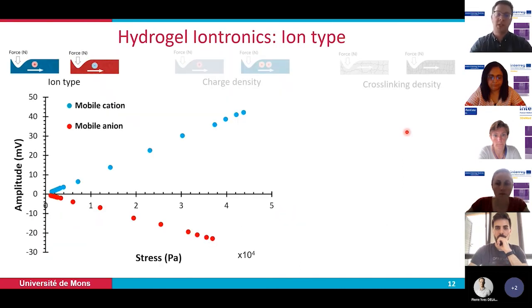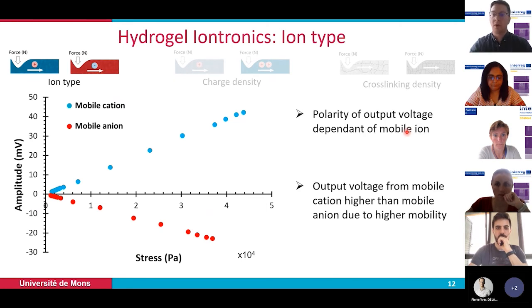First of all, we check the ion type, and the results are as expected. We have a polarity that is completely dependent on the mobile counter ions that we use. If we use a mobile cation, we have a positive signal, and with a mobile anion, we have a negative signal. But what is interesting is that the output voltage is higher for the cation than for the anion. This is due to the mobility of these ions: the cation is more mobile than the anion in our matrix, and that's what explains this difference between the two.